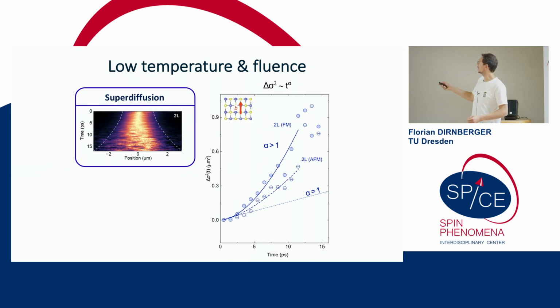And we do see that, again, it's very robust. We see it for the ferromagnetic configuration of the bilayer, as well as for an antiferromagnetic configuration, also for the A and the B direction. So there's a superdiffusion of excitons exclusively happening in bilayers, because if you move the laser spot from the bilayer to just a nearby trilayer crystal, this entire behavior is gone completely.